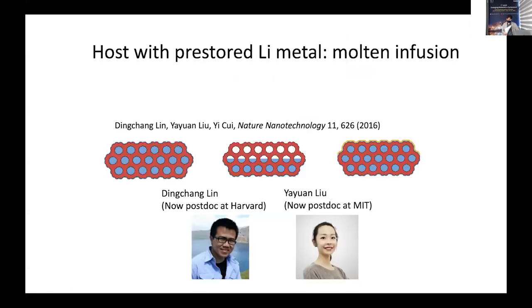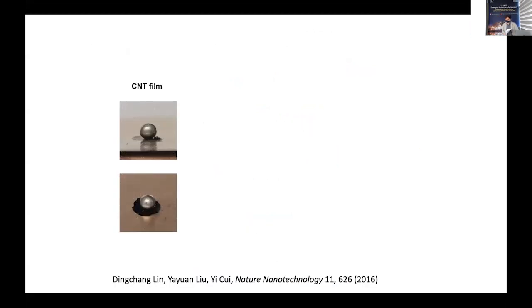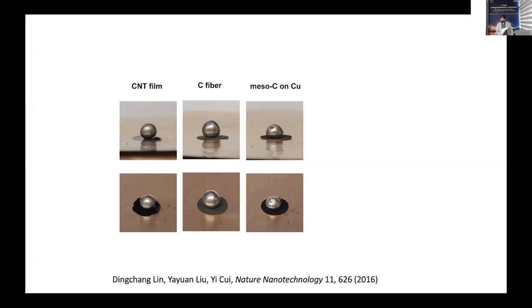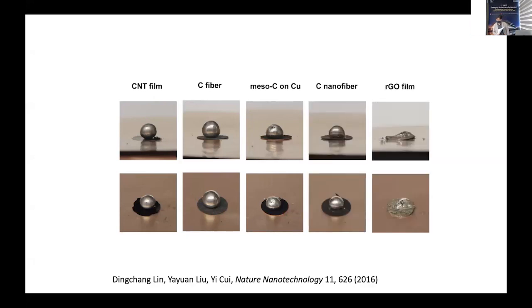So with this initial demonstration, what we really want is to use chemical synthesis to embed metallic lithium into the host. We developed a molten lithium infusion process for the first time in 2016 by these two graduate students, now postdocs on the East Coast. So we melt the lithium, and try all types of carbon host, carbon nanotube host, lithium metal after melting does not like to wet. All types of carbon, they don't want to wet until we try graphene oxide. Graphene oxide wets lithium very nicely.